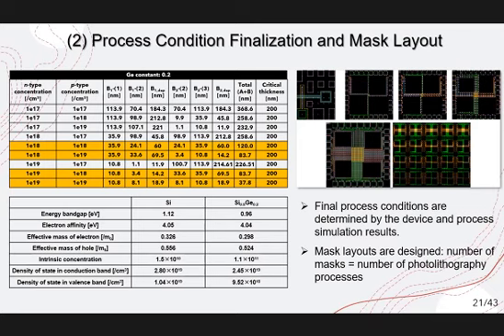For device fabrication, I wanted to introduce 20% of germanium into silicon to have a silicon 0.8, germanium 0.2 alloy. So the final process conditions can be determined by device simulations, but the device simulation results are not always true. So from time to time, even in the fabrication facility, we need to perform test runs and material characterization. Not just at the beginning of the process, but throughout the whole process, we sometimes need to perform those kinds of jobs in the middle of process integration or device fabrication at any time we want.